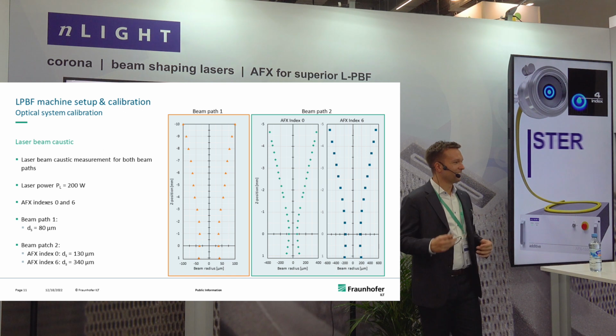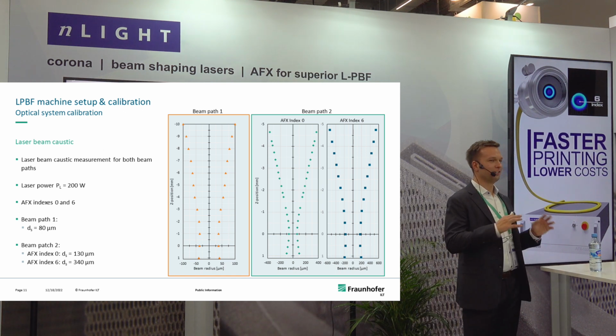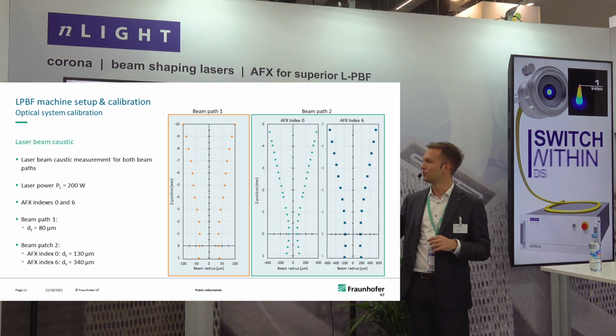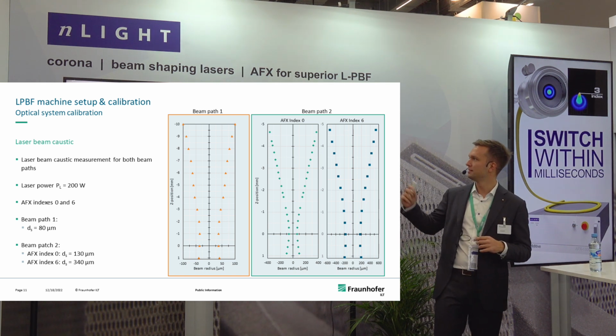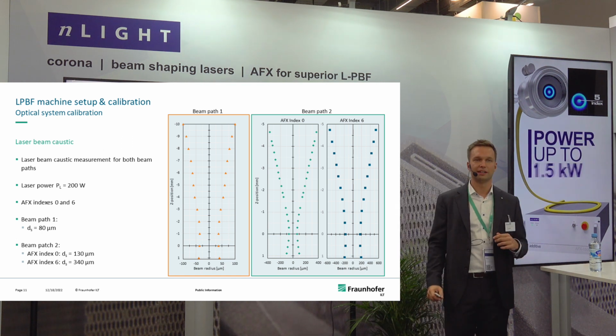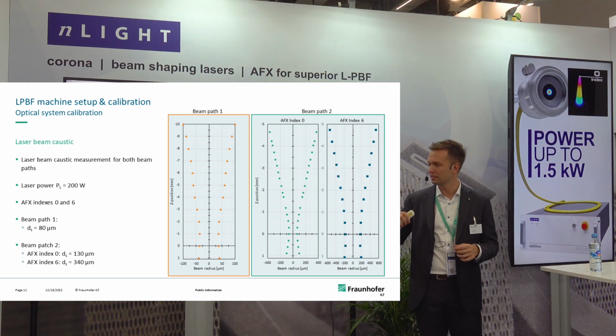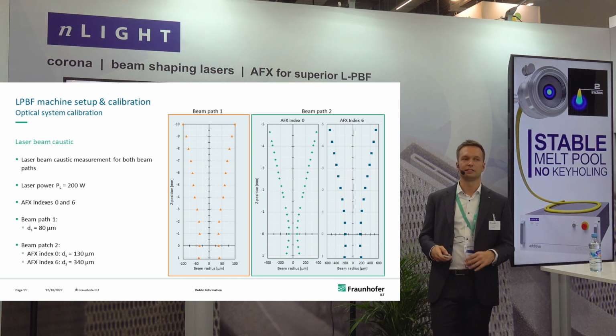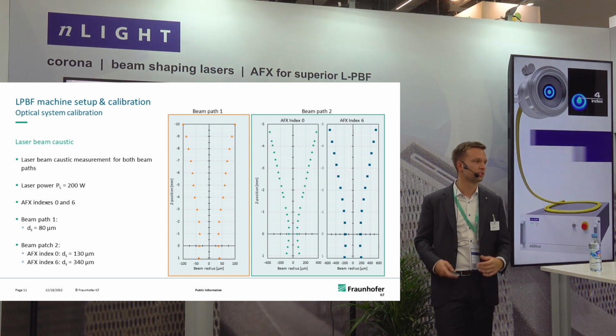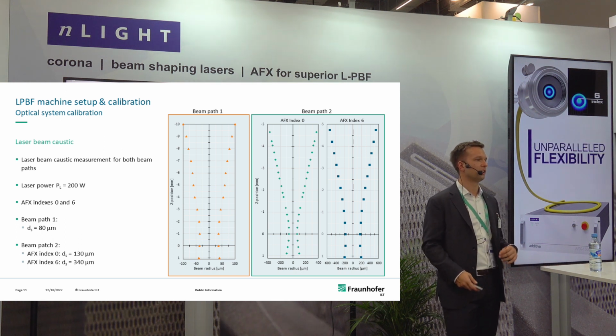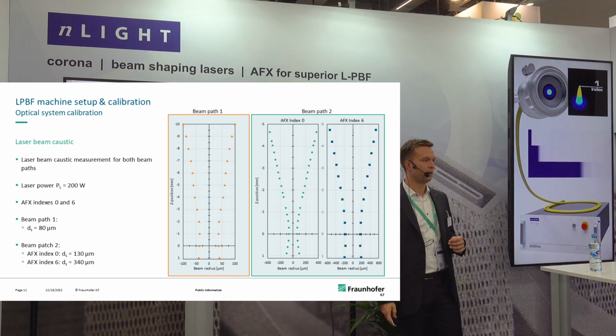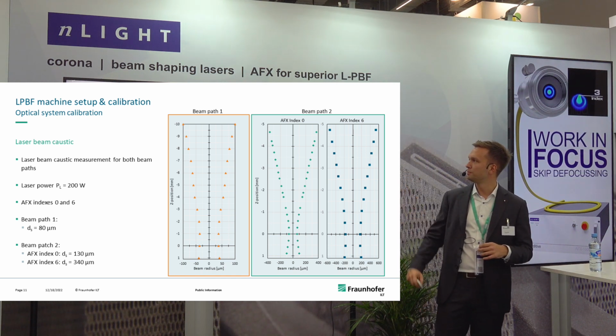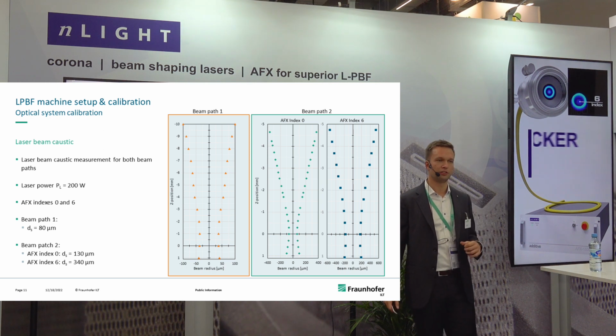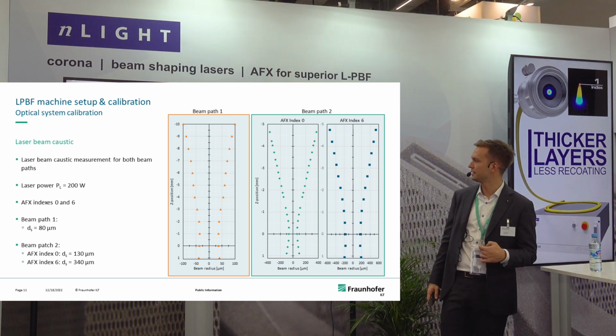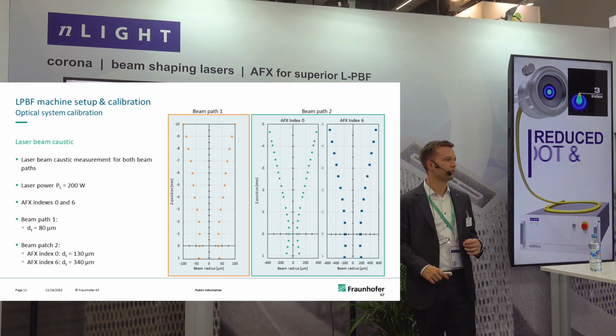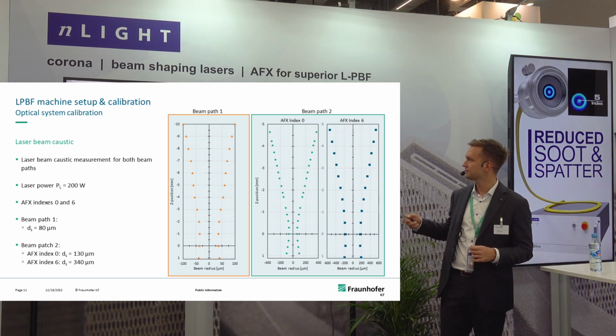Of course, we need to check that it actually works. We have done full characterization of both beam paths. So for the single mode and the AFX, we analyzed laser power characteristics and the caustic. We found that both intensity distribution and laser beam diameter were as expected, so 80 microns for beam path 1, the single mode fiber laser, and beam path 2 in between 130, here for the index setting 0, and 340 for index setting 6.